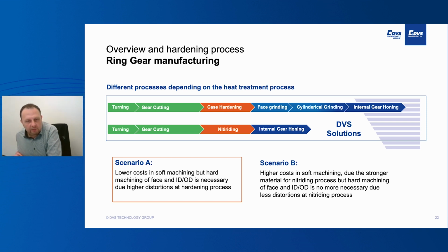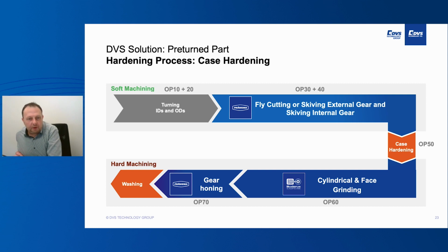In the case hardening process, followed by grinding processes, the process flow will look like shown. We start with the fly cutting or skiving of external and internal gear. This is related to the different designs. Sometimes it's necessary to have also outer gears, which we are doing with a second process like fly cutting. After the soft machining, it's the same case hardening outside of the DVS portfolio. And then we get the parts back to a Buderus grinder and do the grinding operation, face and bore grinding and hard turning. And finally, we have the gear honing, and after that, the parts can go through the washing line.